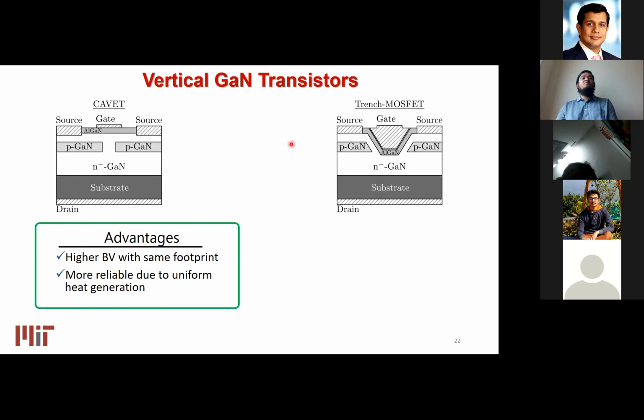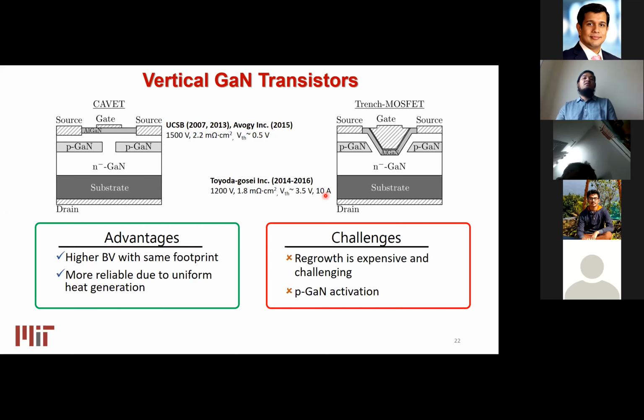But there is a specific problem with this technology for gallium nitride. Although these devices enjoy tremendous success, and people have demonstrated 1.5 kilovolt, 2.2 milliohm centimeter square devices in both structures and up to 10 amps current from a single device, the major challenge is the growth of this P-type layer. From the material grower's point of view, someone grows a thick N-minus GaN up to this point, and then they have to grow the P-type region, do some etching, and regrow the N region on top. This is what people typically call regrowth. So you have to put it in the growth chamber twice. That makes this device fabrication extremely expensive and challenging, and that comes with many other additional problems.